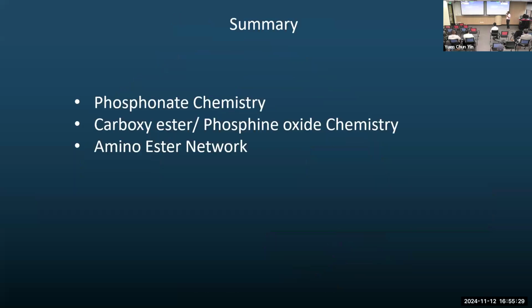So at the end, this is the last slide. I showed you an example of the principle of covalent adaptable networks. These are thermoset polymers, which you can open and close by using different triggers. In our case, we are using a thermal trigger to rearrange the polymer. You can also use heat and light. We are focused on this phosphorus-based chemistry where phosphorus-oxygen bonds are reversible. We have also used carboxy ester chemistry. More recently, we are working on amino ester chemistry where you make a nitrogen-carbon bond, which is reversible in nature.